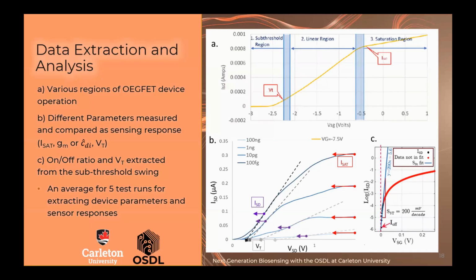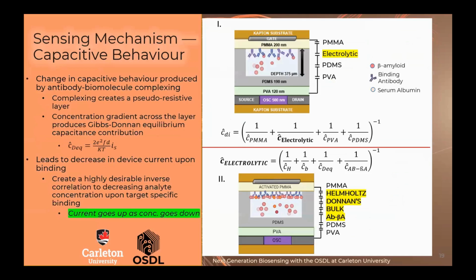In terms of parameter and analysis, we have simplified it because we want to make it portable. Initially, we were doing all kind of complex Marino model, curve fitting, extensive data extraction. Now we are looking at just 3 parameters. So the saturation current level, the midway of the linear region, which correlates to transconductance very well, so capacitance from there. And we're looking at the subthreshold swing to kind of confirm that the threshold, the turn on and on off ratios remain comparable.